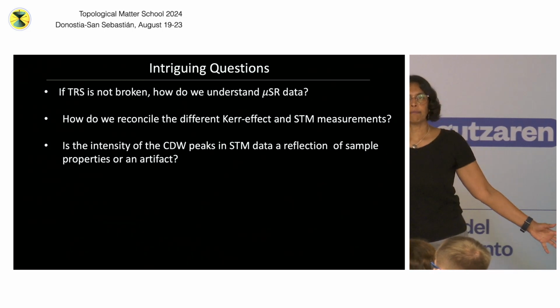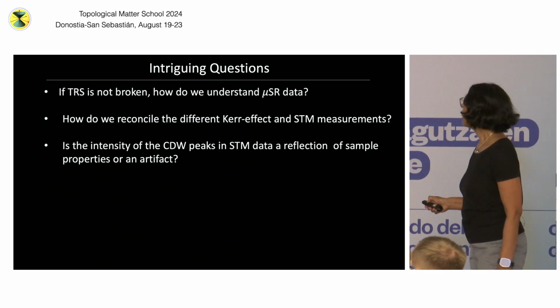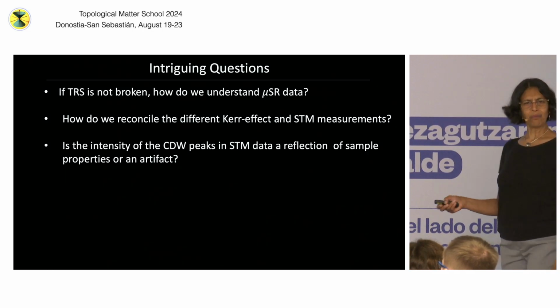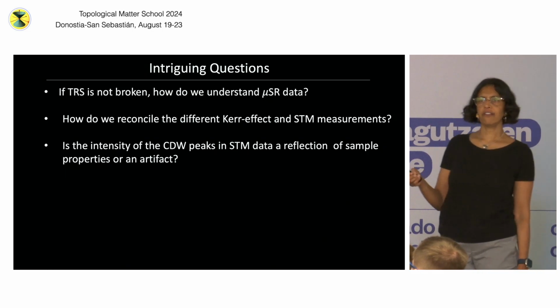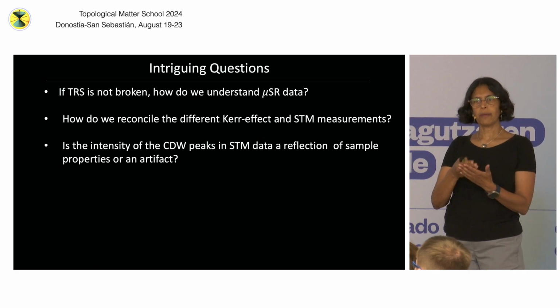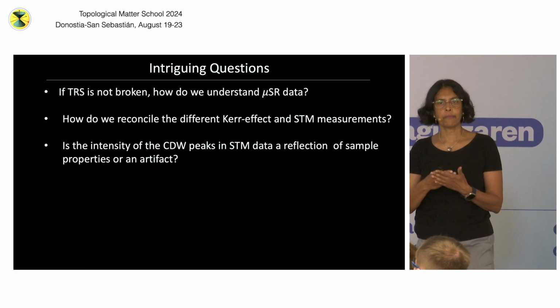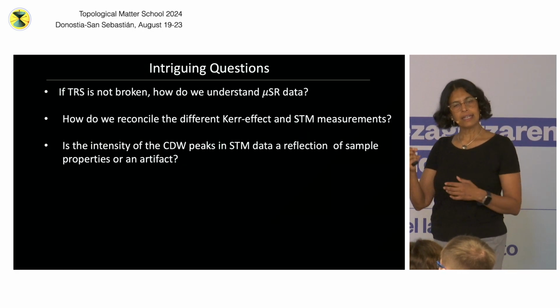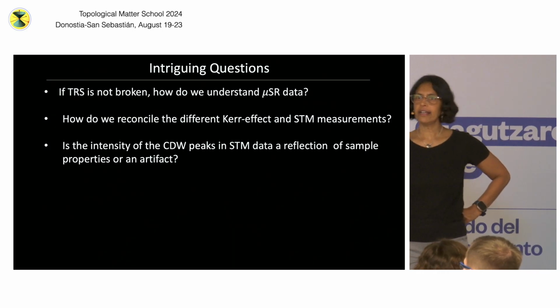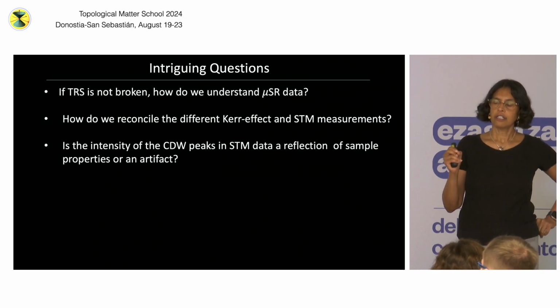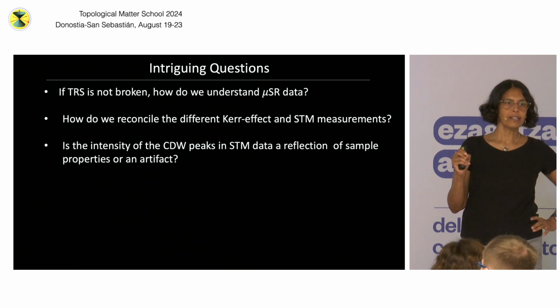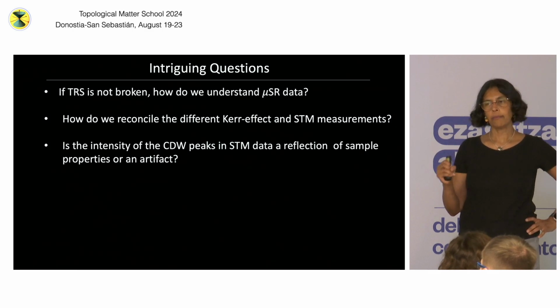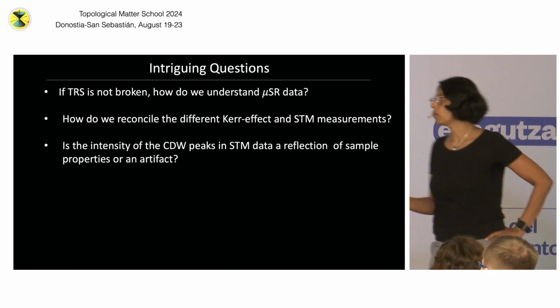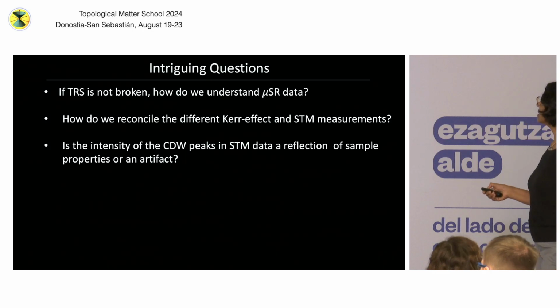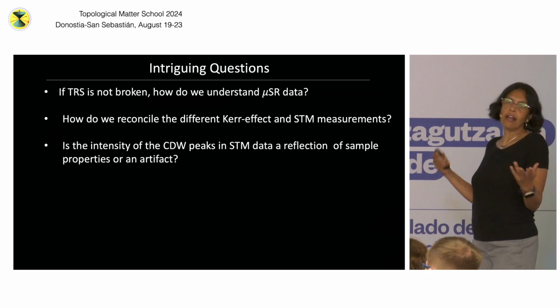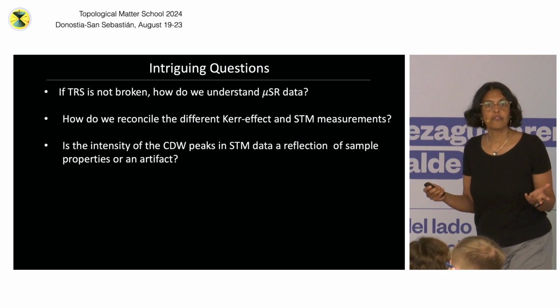Different groups are measuring completely different things. And also, what is this intensity of the charge density wave peaks in the Fourier transform in STM data? What does that actually represent? Does the intensity capture the strength of the order parameter, the charge density wave order parameter, right? Does it actually capture the order parameter in a system? That's the question that we would like to answer. Or is the height of this Fourier transform peak an artifact? Maybe it's got something to do with the tip.